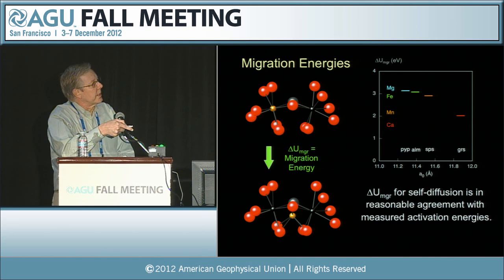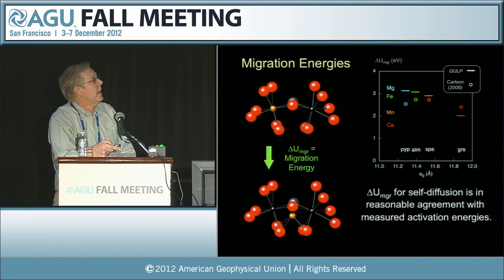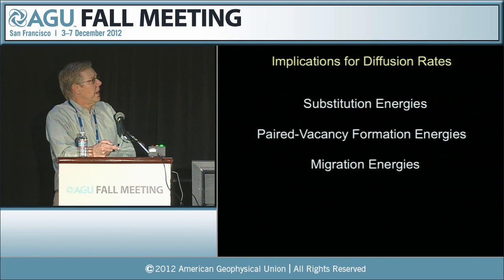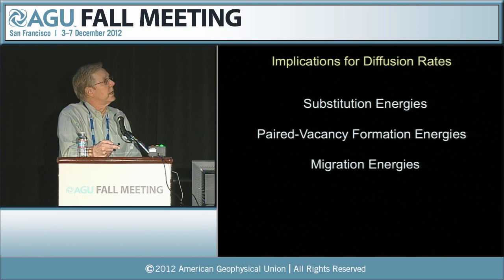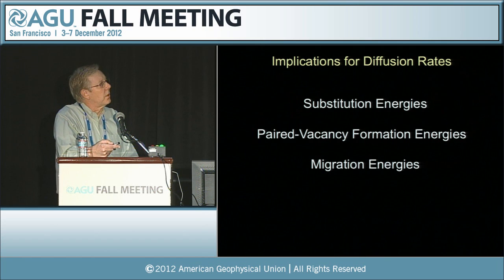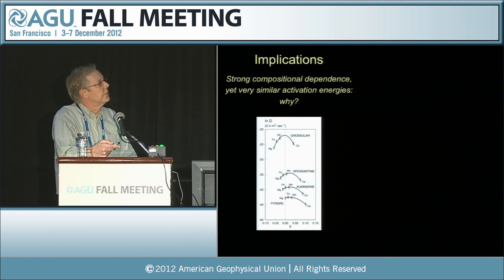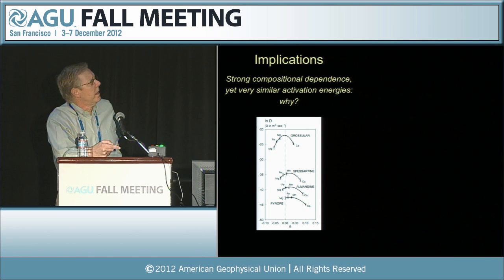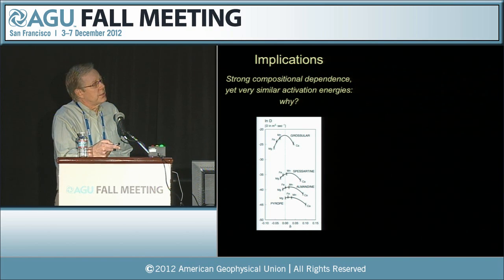In passing, if we look at self-diffusion and what these migration energies are, they are actually in reasonable agreement with measured activation energies, although they're not exactly the same thing. So I'll close here by looking at what the implications of these things are for diffusion rates, each in turn. Starting with this strong compositional dependence. We observe strong compositional dependence, but with very similar activation energies.